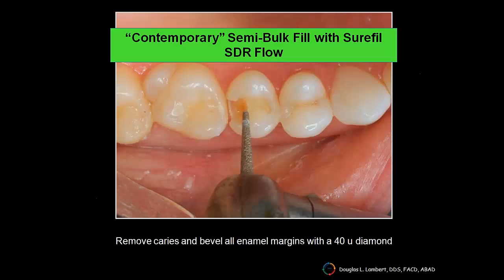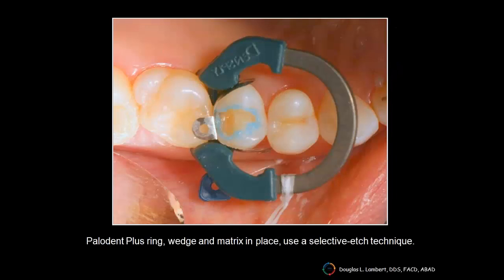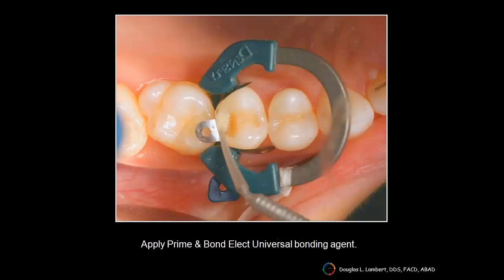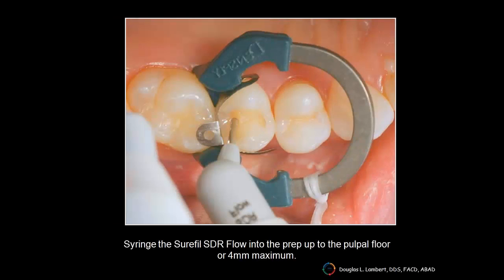So let's walk through it together and step by step. We're going to do the contemporary semi-bulk fill technique with SureFill SDR flow. We're going to bevel all the occlusal margins after we remove the caries with 40 micron diamond. We're going to isolate the tooth preparation with a Palodent Plus ring, a wedge, and matrix of choice. And I'm a big selective etch person. I will selectively etch that enamel first and then follow up with a universal dentin bonding agent according to manufacturer's directions. Air thin that, cure it again according to the directions of the manufacturer.